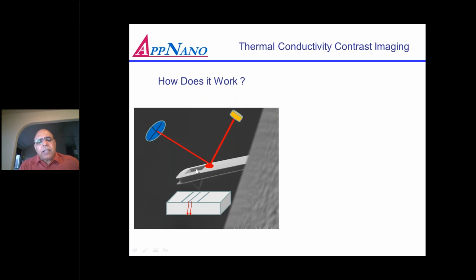Normally we don't take this precaution when we are using the probe in topography or other applications, but here this is important, because if you want to measure temperature, you don't want to influence the thermocouple with the laser heating. Normally the laser which is used for most AFM is about 1 milliwatt, and 1 milliwatt can raise this temperature up to about 100 degrees Celsius. So just be careful. Depending upon how you focus, the temperature can be less or more, but one can easily get a 10 to 20 degree temperature increase when you have the laser on the thermocouple.